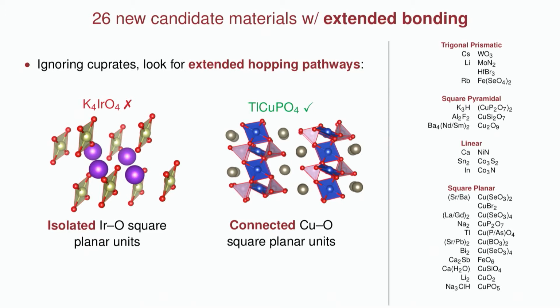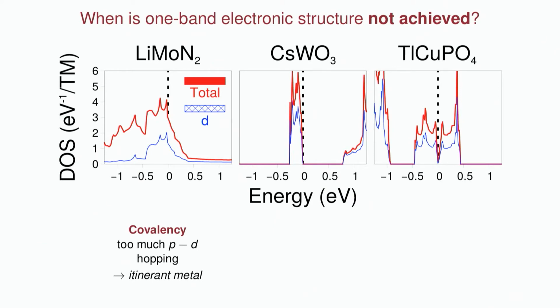It turns out even that is not sufficient to ensure that we'll get this single band correlated material properties. And there are a few things that can still go wrong at this stage. Basically, a few ways in which nature can still avoid this rare feature of a one-band model. And I'll describe those here. So the first thing that can happen is the material can just be too covalent. Basically, as exemplified by this nitride material, there can be too much interaction or hopping between the transition metal d states and the anion p states, such that we just get this delocalized, broad metallic band. So we just have your usual itinerant metal.